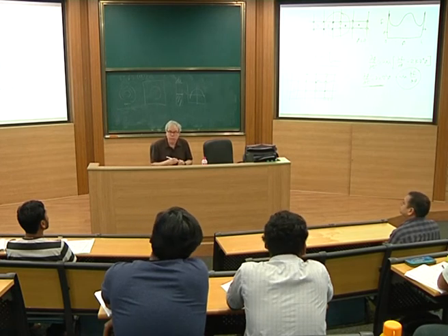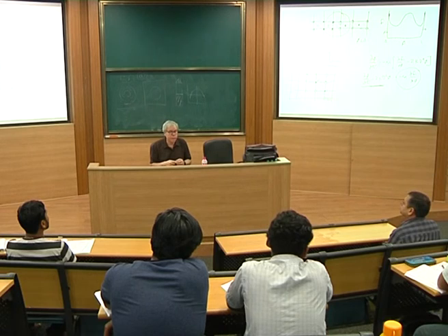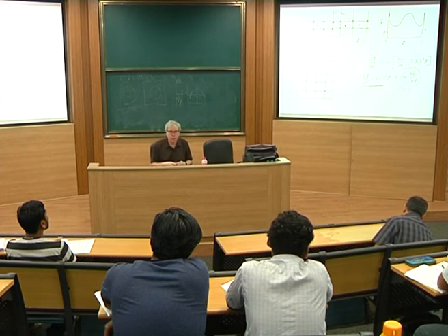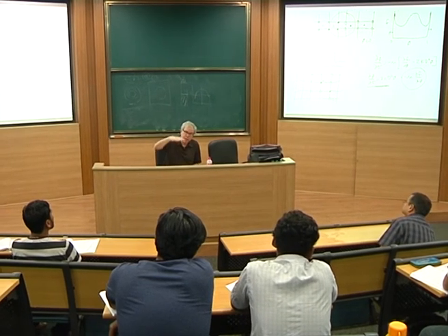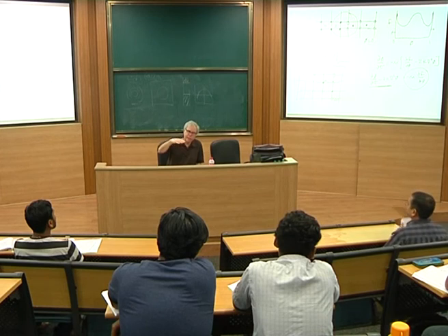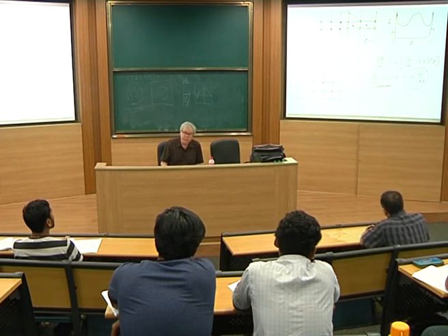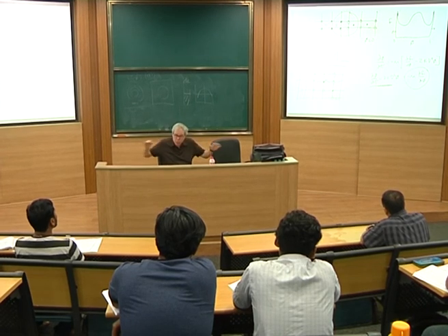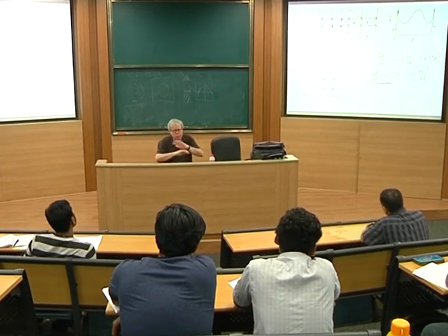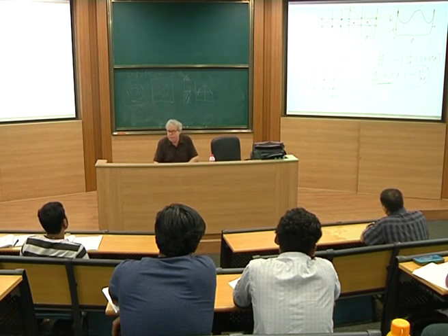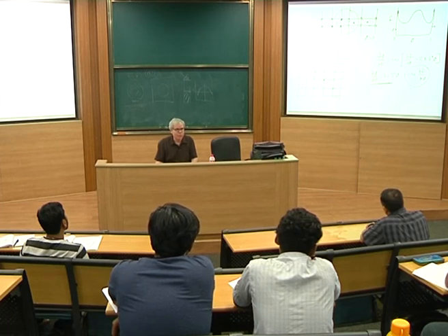There was a fellow at Argonne, by the name of Brian Stevenson. He was an X-ray synchrotron person, and he worked very hard to do ultra-fast quenches into spinodal regions to see if you could measure the structure function or the composition fluctuations to see if the linear theory holds. And he did millisecond quenches, and he still didn't see the linear theory. Even though the composition fluctuations were extremely small, you were almost uniform, and he worked very hard to worry about vacancy concentrations. It was a very hard experiment. He still didn't see the linear theory. Kind of an interesting question.